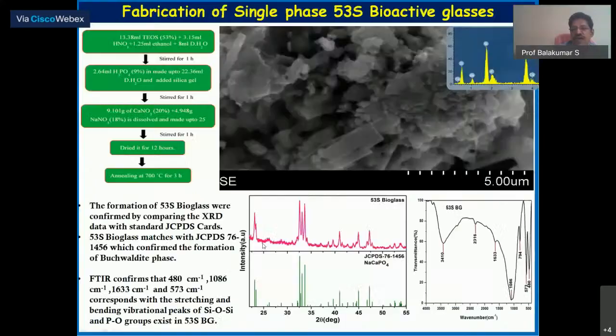But what we have done is we have been working on this material for 10 years, and we took a new composition, where you want to have a single phase bioglass, it is 53S. 53S is a name we developed. We developed this material in bar shape and systematically studied the properties, and we developed a membrane type of structure earlier. This is with the 45S, and later with the 53S bioglass we developed a corneal membrane. One of the properties is transparency. The maximum transparency we have achieved so far is 90%. We have to go very close to 95.